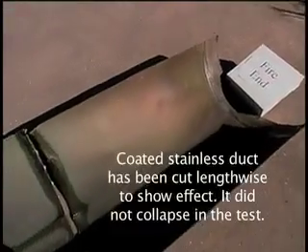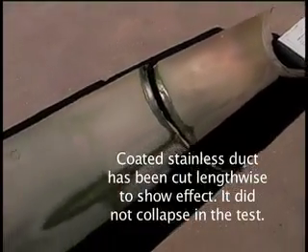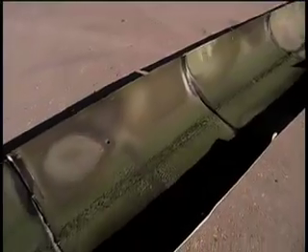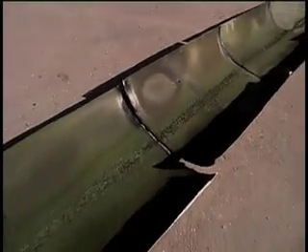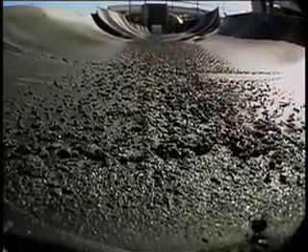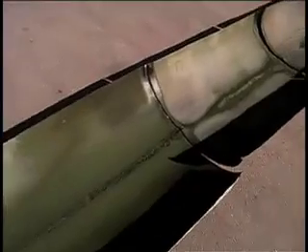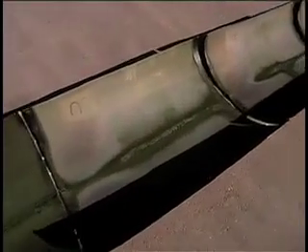In this test, the clear ETFE coating melted, pooled at the bottom of the duct, then caught fire as the temperature exceeded the flashpoint. The temperature at the fire source exceeded 1500 degrees Fahrenheit. The ETFE coating melts at approximately 500 degrees Fahrenheit and ignites at 878 degrees Fahrenheit. Droplets of the melting ETFE coating were sucked into the air stream and pulled toward the fan.